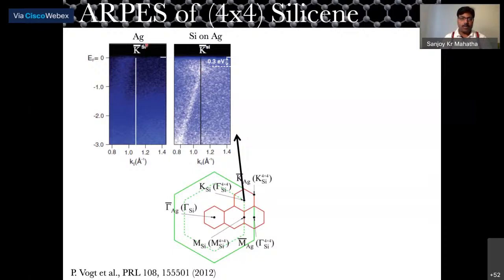So you see, they have shown the silver spectra near the K point of silicon. There is no band, and after putting silicon, they could see a linearly dispersing band up to 0.3 electron volt. And then they claimed that this must be the silicene Dirac cone at the K point.